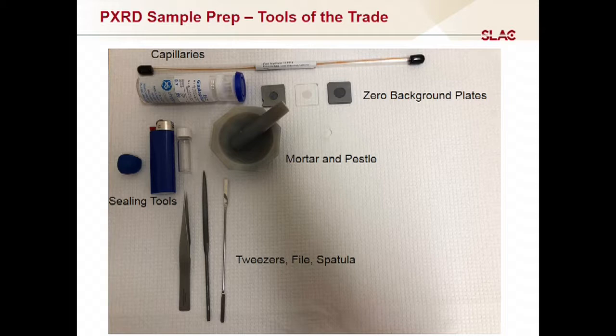It also requires less sample. You don't need very much to fill up a capillary. And after you've sealed it, it's just there. You can stick it in one of these little scintillation vials, and you have it forever. If you mount a powder into one of these zero background plates, when you're done, you have to dump it out, store the powder. That same sample can be remeasured, but not in the same way that you loaded it the first time. If you have a capillary, the capillary is not really changing over time, assuming your material is stable. It's also a good way of sealing your material, especially if you use one of the glass capillaries. You can seal it in a controlled environment. So if it's an air-sensitive sample, you can seal it inside of a glove box, and it will forever be in an inert atmosphere that way.